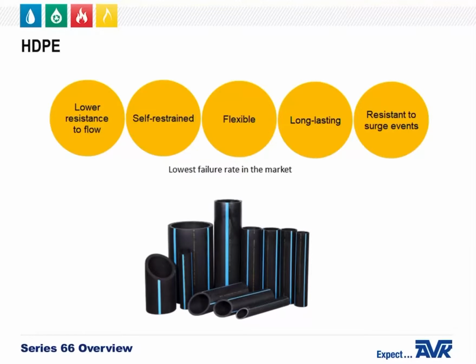Why is HDPE gaining popularity, and what are the key advantages over iron pipe? PE pipe can absorb 2 times its maximum operating pressure if a surge event such as a water hammer occurs. Due to the flexibility of PE pipe, the water hammer energy is absorbed quickly and does not cause damage to the more rigid components of the pipe system. Ductile iron and PVC pipe, on the other hand, are very rigid and will therefore transmit the water hammer energy a great distance through the pipe until the energy finds a weak spot in the pipe and may rupture the pipeline.